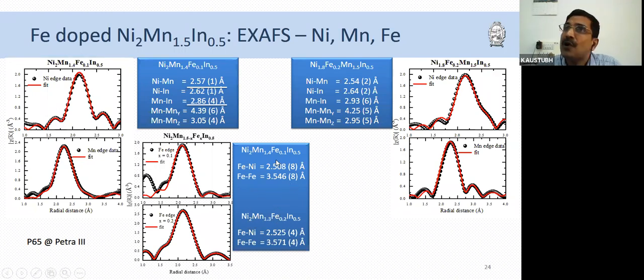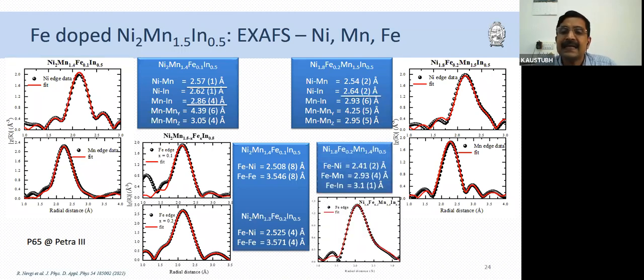So instead we got iron-nickel and iron-iron at these distances, which are characteristic of a face-centered cubic lattice. These distances, if you take the ratio, they're exactly face-centered cubic. So the FCC phase that we saw in synchrotron XRD, we could say that that is coming from a gamma Fe-nickel phase.